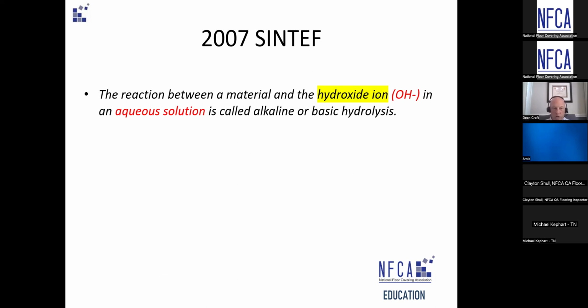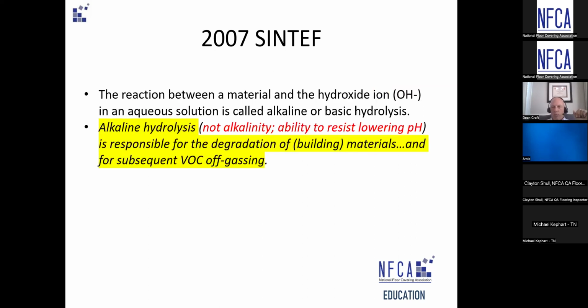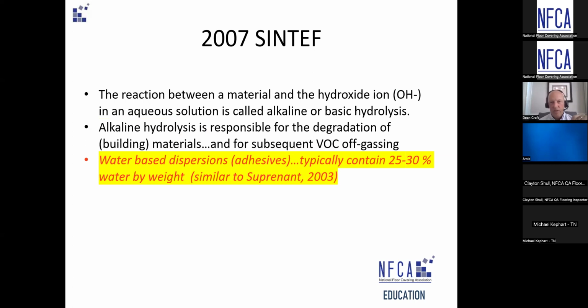Regardless of what caused the liquid to happen or the alkalis to go into solution, whether it's moisture vapor emission, condensing, or the adhesive itself contributing the moisture, once that solution goes to a certain level of basic pH, 11, 12, there's a good chance it's going to start attacking the chemical makeup of that adhesive or product. That's really what leads to the breakdown and even VOC off-gassing. These hydroxide ions attack the adhesive or the backing and turn it to goo, but it also releases alcohol, which causes odor in the VOCs. So you have a downward spiral, but it's not the alkalinity, it's actually the elevated pH of the solution.